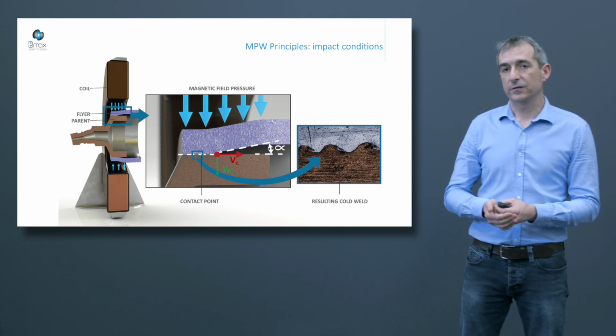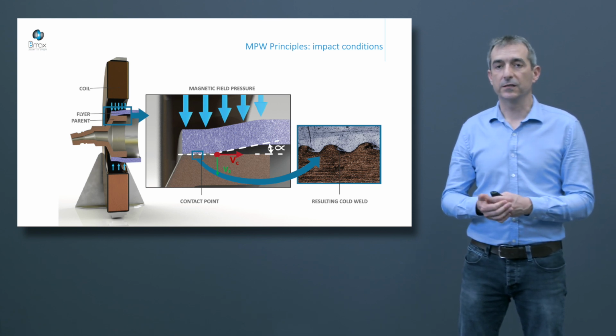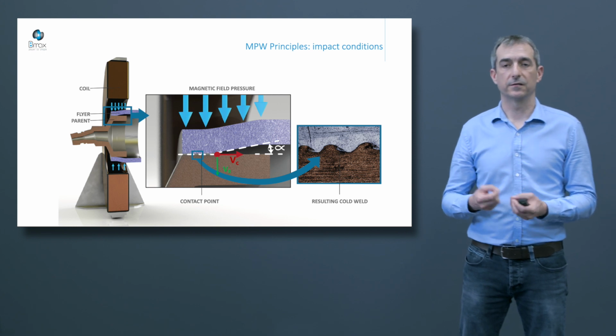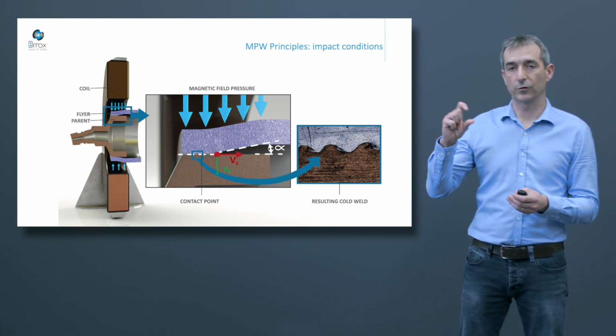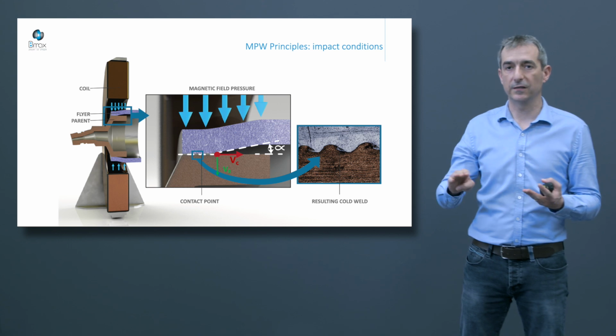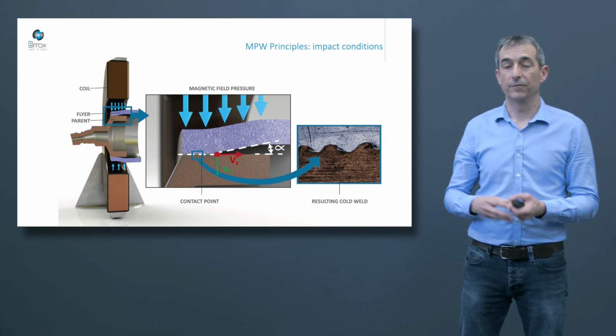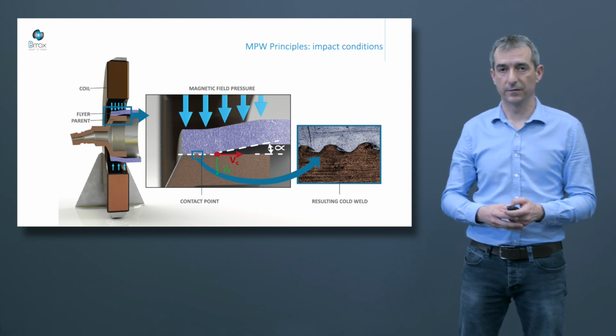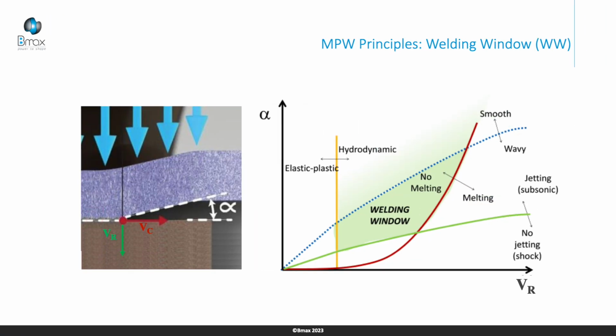In magnetic pulse applications, in magnetic pulse welding, this velocity is not constant. That's why we use the component of the speed normal to the interface, to the contact surface, VR, in red on this screen. In this way, we are able to define magnetic welding windows, the conditions required to expect a weld. The drawing represents these parameters, angle and speed, and normal speed to the interface.